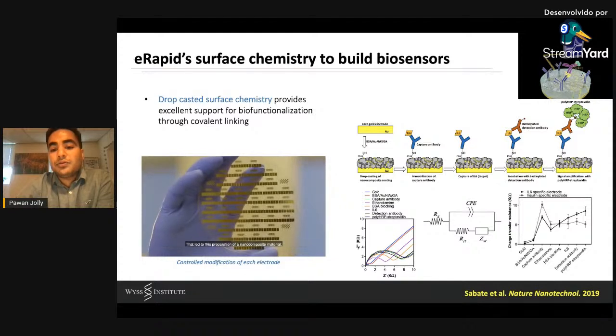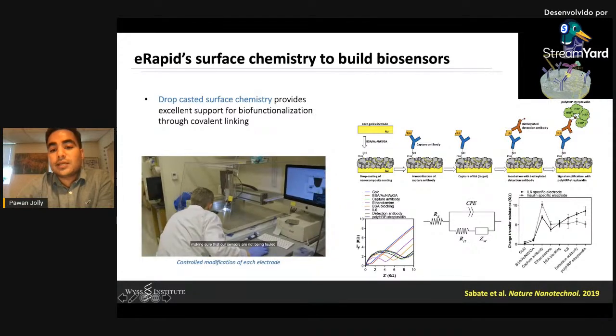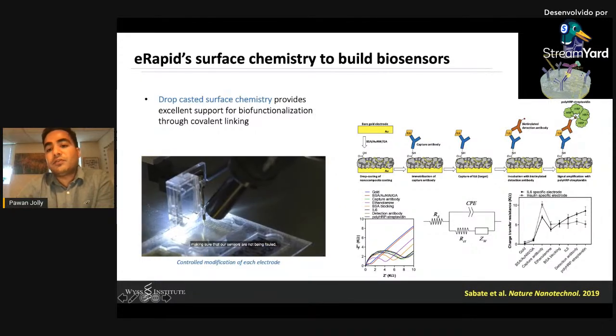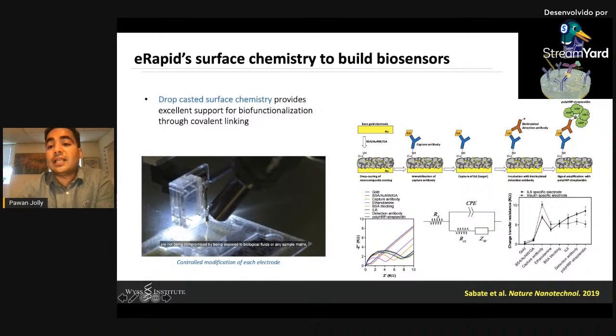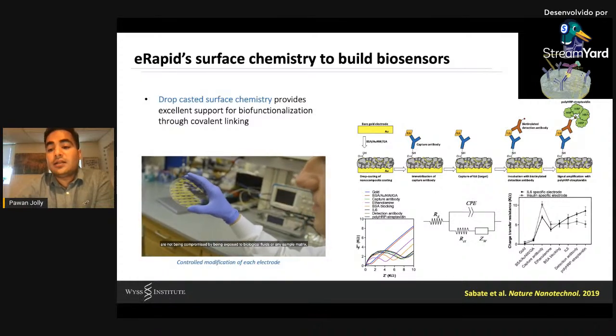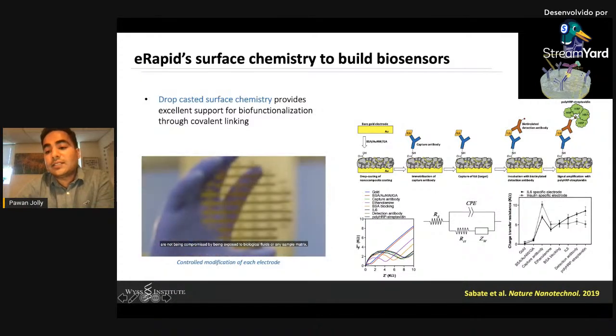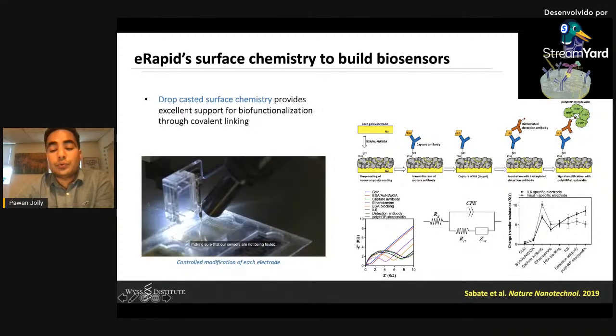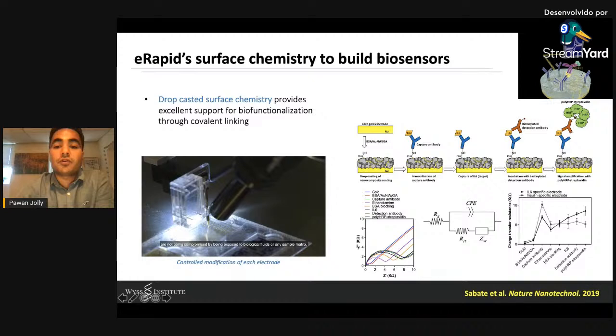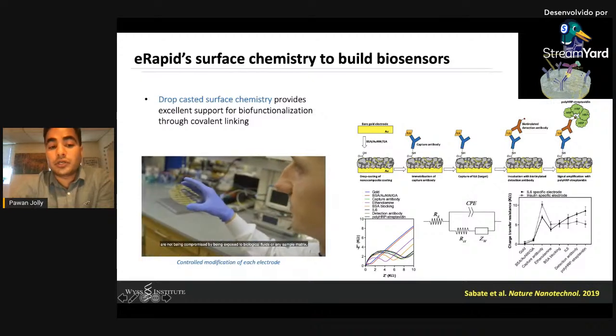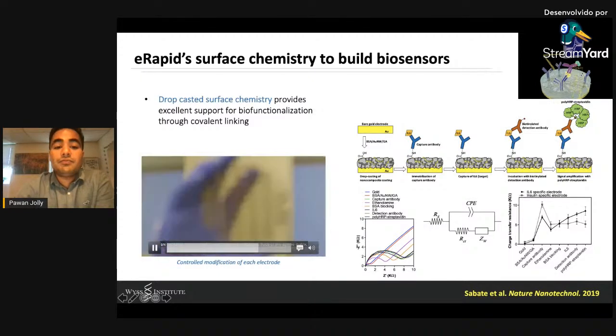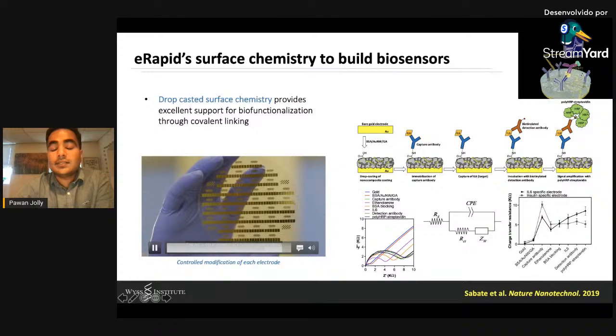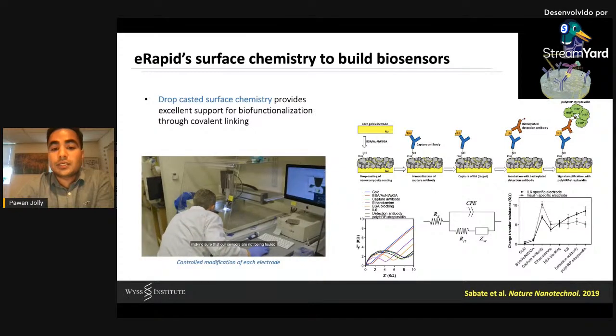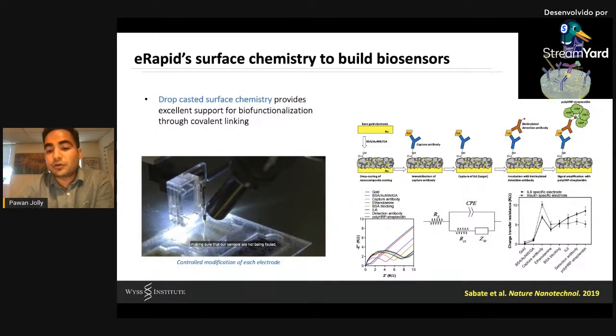So over here, what you see is you can actually do step-by-step modification of the surface and perform the whole sandwich ELISA on the surface. And on the EIS result, you can see a very specific binding of a specific sensor, while no non-specific binding from our non-specific or the control sensor. And on the left, what you can see is how we coat the sensors. This can be easily inkjet printed to actually enable mass production of these devices.